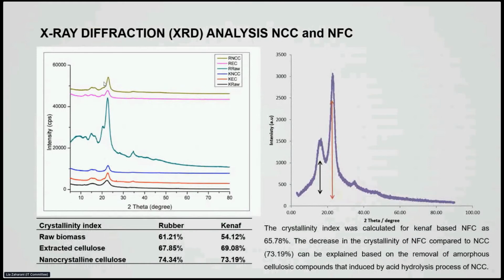We ran XRD analysis for checking the crystallinity. Raw biomass gives nearly 60. After extraction, cellulose gives a little bit higher crystallinity. The highest crystallinity is from the nanocrystalline cellulose, which is almost 60 to 70. Comparing nanocrystalline cellulose and nanofibrillated cellulose, nanocrystalline cellulose gives a little bit higher crystallinity than nanofibrillated cellulose.